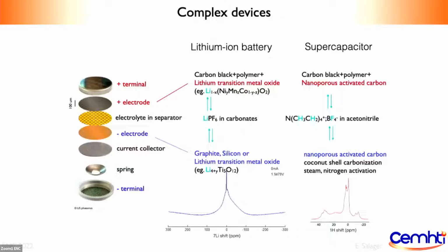They're actually quite complex. So you have different parts. It's a very heterogeneous device, but they're all based on the same principle. You have a positive electrode, a negative electrode, and some electrolyte, usually liquid, that is soaking everything. The ions can equilibrate the charge by passing through the separator, and the electrons go through the outside circuit, and that's your current. In the case of lithium-ion batteries, there are redox reactions at the positive and at the negative electrode, and at the same time, lithium ions are moving back and forth. So we have lithium everywhere in there. If you look at an NMR spectrum of lithium, what you get is a superposition of the two contributions. It's very difficult to tell anything out of it just by looking at the spectrum.